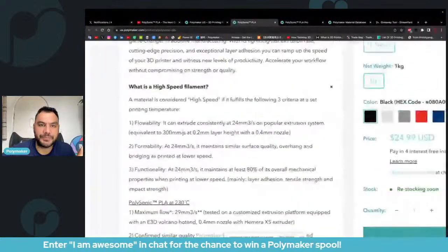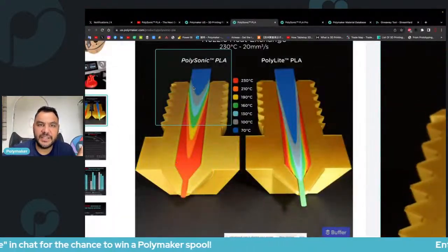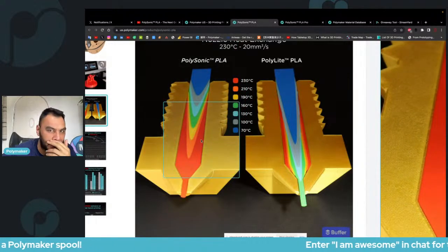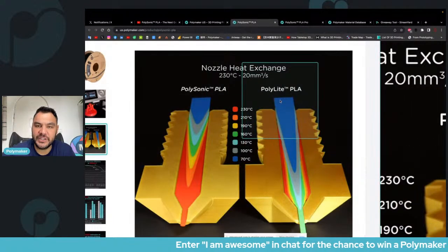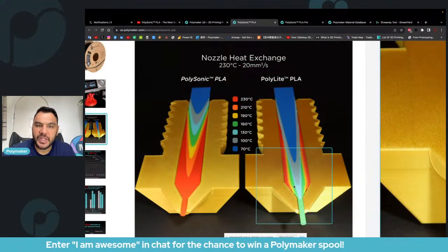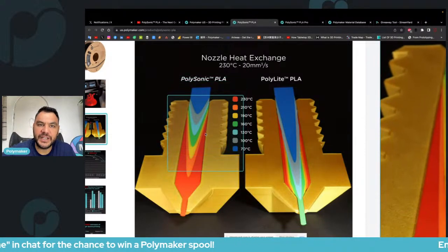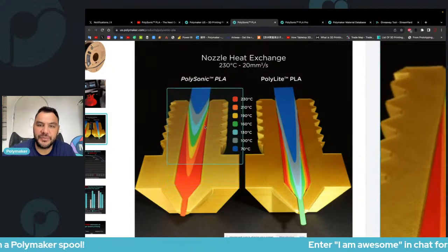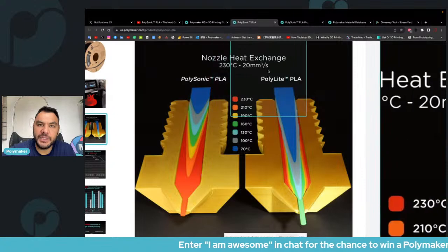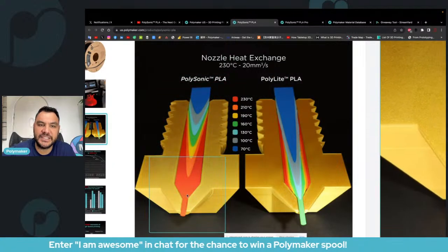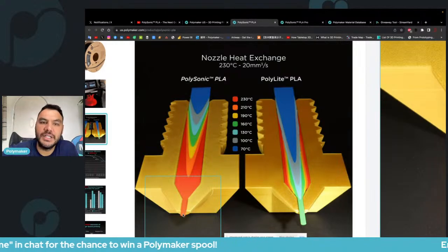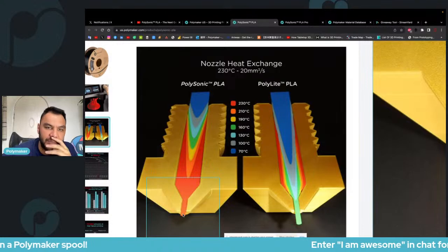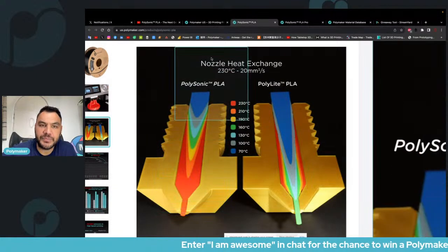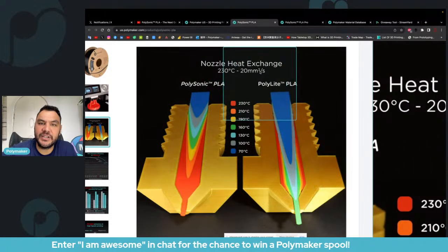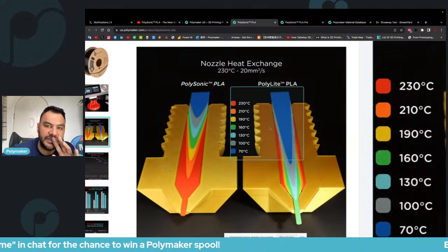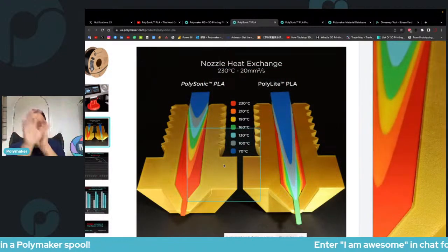For example, you can see here, Polysonic PLA melts much faster. They all go at the same speed, 20 millimeter cube per second. So they flow at the same speed. But the fact that Polysonic PLA melts much faster, heats up faster, means that even at 20 millimeter cube per second, it has time to reach 230 degrees C before reaching the nozzle. But now, let's say you have a high flow extrusion system, then maybe the chamber is much longer. If the chamber is much longer, then at 20 millimeter cube per second, even Polylite PLA will have time to reach 230 degrees C before the extrusion. So you can see how everything kind of interacts together.